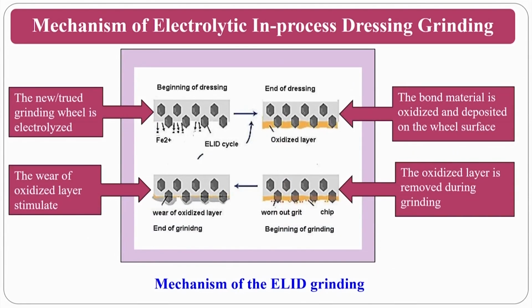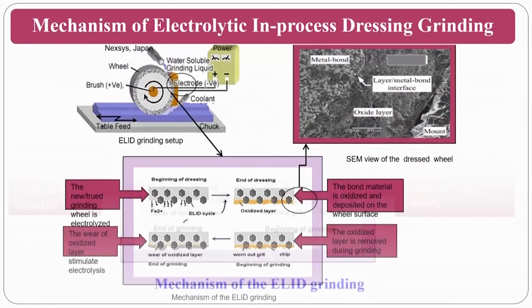If you see here, these are the 4 stages. One will be the beginning of the dressing. At the ending of the dressing, you will have the oxide layer. During or at the beginning of the grinding, this oxide layer will wear out and the grinding will take place, and then wear of the oxide layer at the grinding ending. Okay, you see here completely the summary of this electrolytic in-process dressing based grinding process.